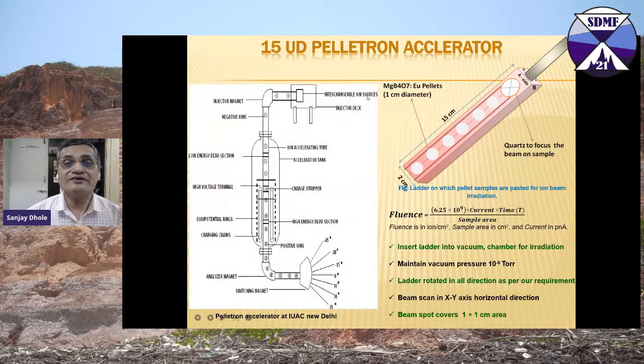So this is the 15 UD accelerator, which is available in the Inter University Accelerator Center, New Delhi. Here there is an ion source, and this is a tank where the acceleration takes place. You can have a negative ion from the ion source, which is an RF ion source initially, and which can accelerate up to 15 megavolt. Then there is a stripper made of carbon, which is very thin. The ions interact with this and transfer their charge, and this becomes positive ions. Again it accelerates, and it becomes 30 MeV.